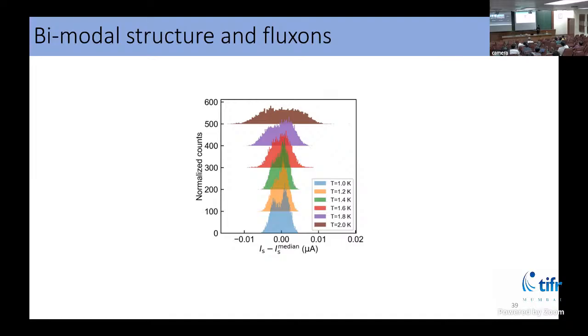Basically, when we are increasing the temperature, this kind of superconductors are essentially type 2 superconductors. So there is influx of vortices. Now, you can imagine a state where I am at this 1 Kelvin temperature, and I have this network of Josephson junctions. Now, this vortex is present in one network, one circuit of Josephson junctions, whereas it's not in the second. That will affect how my Josephson junction switches. So in a sense, I have created two parts of my system, which will switch at two different currents, because of the presence and absence of vortices in one part versus the other.